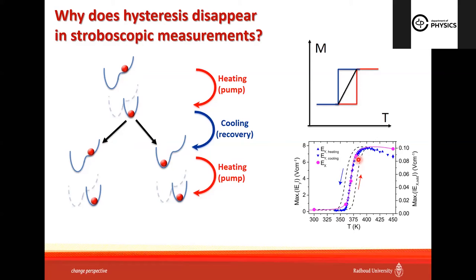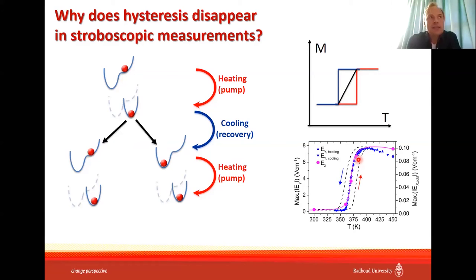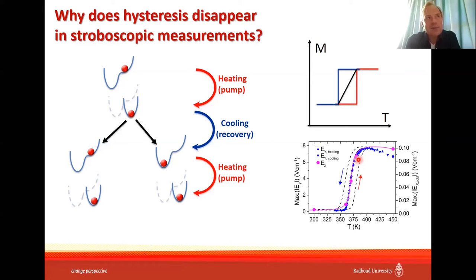Excuse me. Question. Yes, Sasha? Sorry for the interruption. Do I understand correctly that in this picture, if there is a really long cooling time, then the hysteresis will show up again? Very long cooling time, maybe, yes. The system will have time to go from the metastable state to the stable state. I would say very long cooling time, and it would be best if it is cooling to a temperature where the second state doesn't exist. Oh, okay. So you really have to restore.